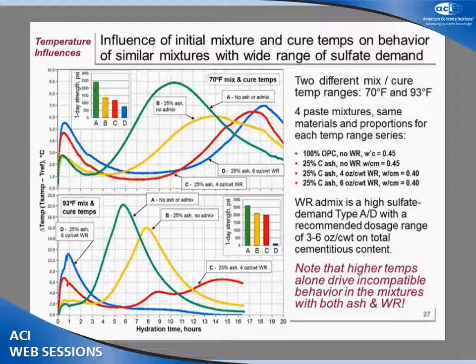Here are four different mixtures, different sets of materials, different admixtures, which at laboratory temperatures all perform normally: one straight cement, one with 25% C ash, one with the ash plus a nominal dose of a lignosulfonate, and then one with a high-range, high-end dose of a lignosulfonate. All of these are still performing normally in one-day strengths at laboratory temperatures, but at 93 degrees Fahrenheit, the mixture with the highest dosage of admixture is now in complete incompatible behavior. So temperature alone can drive whether or not this is a problematic occurrence.